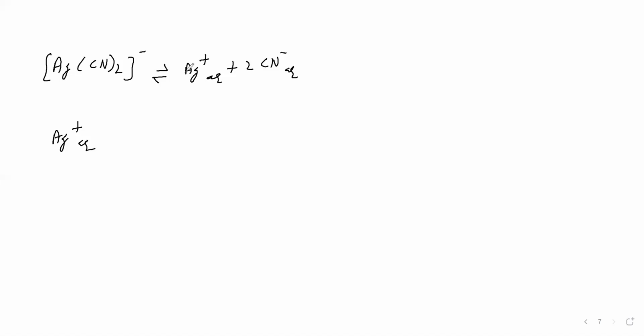So as soon as Ag+ is disappearing, that means going towards the cathode and depositing as Ag, here Ag+ is being created. So the Ag+ concentration will be uniformly maintained here, but not in the simple salt. Initially it is high, as time passes, the concentration decreases. Therefore, coating silver using the simple salt is not smooth, here it is smooth.